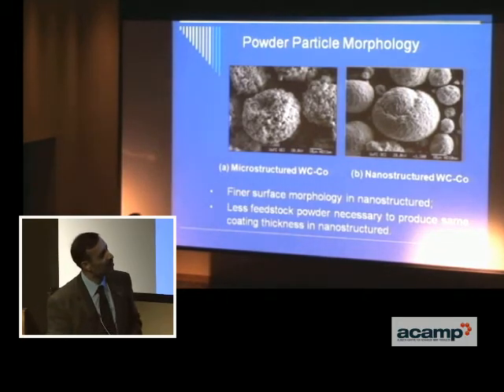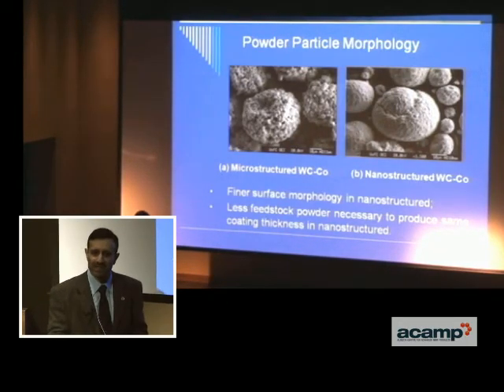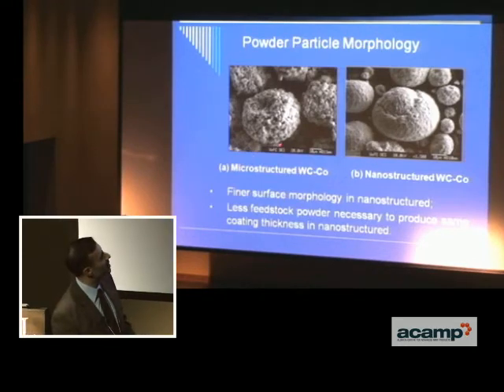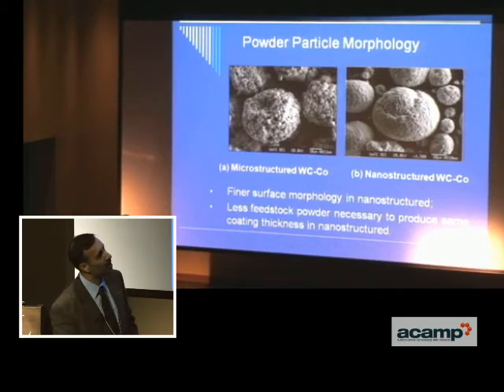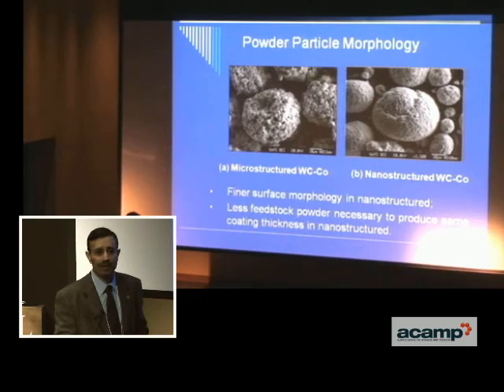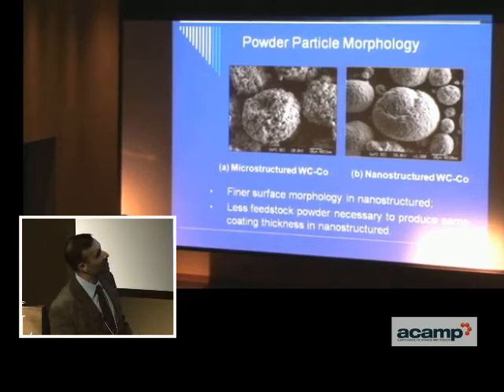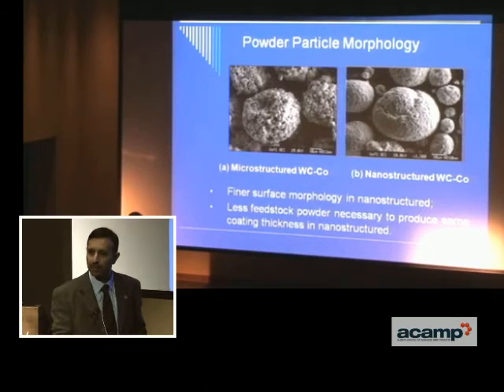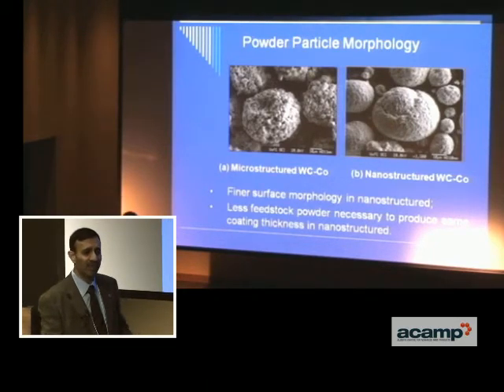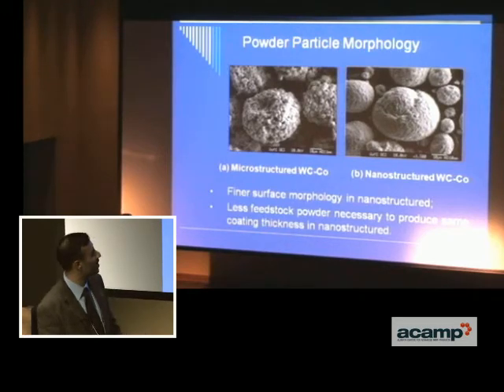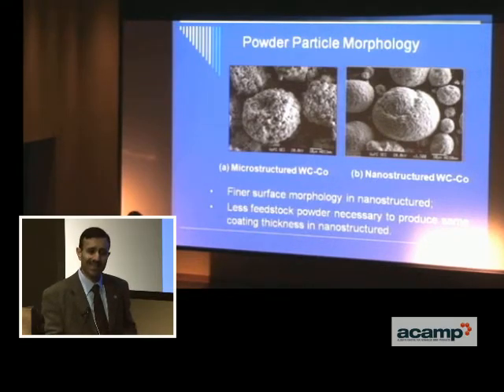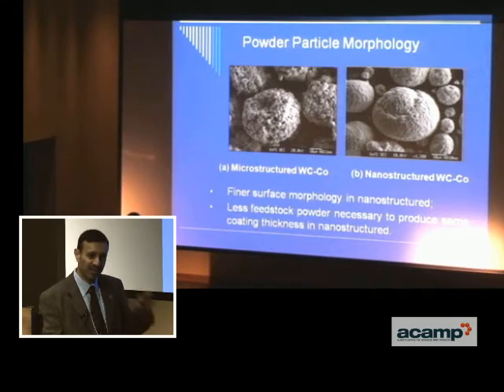So this is just to give you an idea of the kind of surface morphologies and the sizes that we're dealing with. This is a microstructured powder, and this is a nanostructured powder which has a cobalt layer on the outer surface as well. What we see is that the powder finish is much finer with the nanostructure, and that has some unique effects on the processing, the spraying process itself. What we find is that the feedstock powder can be sprayed more efficiently. There's less coagulation or starvation when we're trying to spray some of this powder, and the overall spraying efficiency is increased as well.